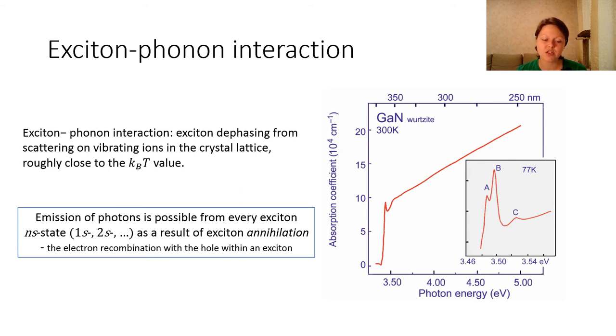The pronounced exciton peaks cannot be observed at room temperature for most typical semiconductors because of the strong temperature-induced broadening of the lines that smears resonant peaks, and also because most excitons ionize into electrons and holes separately. Ground exciton states typically can be observed at 77 K, which is liquid nitrogen boiling point.